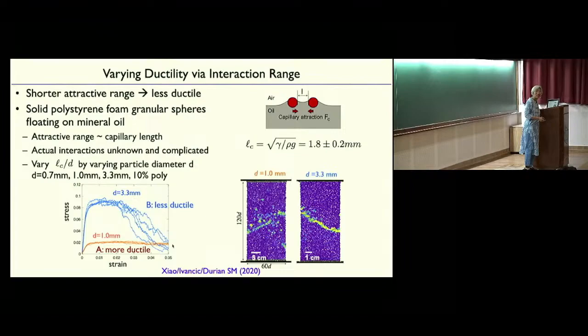I think there were foam experiments by Michael Dennin from about 10, 15 years ago, where he studied the ductile to brittle transition in foam, and he showed a strain rate dependence on this. Did you vary the strain rate here, or was it done quasi-statically? This is quasi-static. Which is different from Kai's experiments, where she varied the rate. Yeah, very nice experiments.